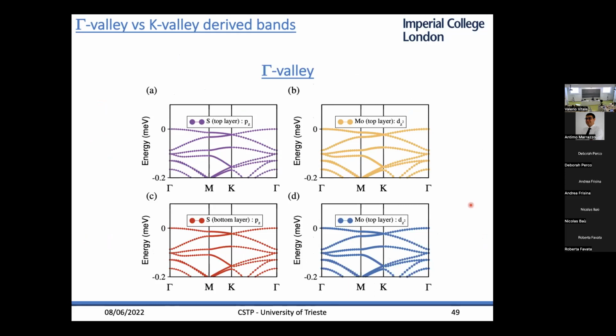Right. So what happens is the following: when you twist the material, you have these two bands forming at the top of the valence band. These are Moiré bands, and in most of the systems these bands are on top of the valence manifold. These bands come from the gamma valley, so they have a high projectability on the pz and dz squared orbitals of your systems.